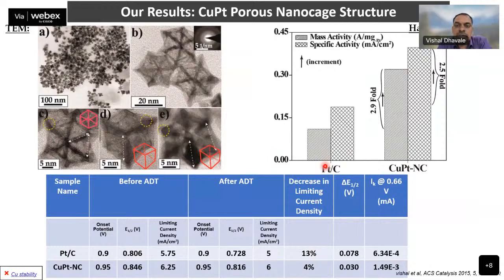So another 5 minutes I have. So our own results, you can see we started with the copper platinum nanoporous structure, where we started with the copper as a copper cage first, and then we started de-alloying this copper by controlled reduction galvanic displacement reaction to get such kind of open frame structures. So you can see the same kind of nanocage structures at a different viewing angle. We can see over here the very open architecture network and the connectivity. Also, you can see the arms of these Pt-copper alloy structures.